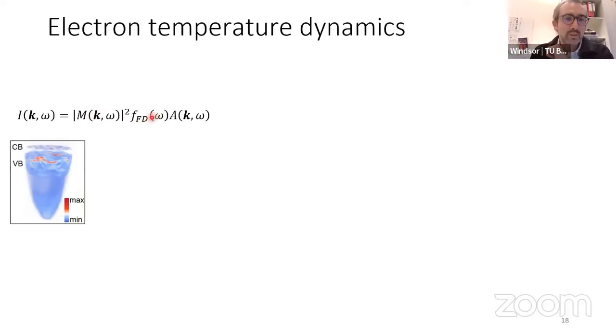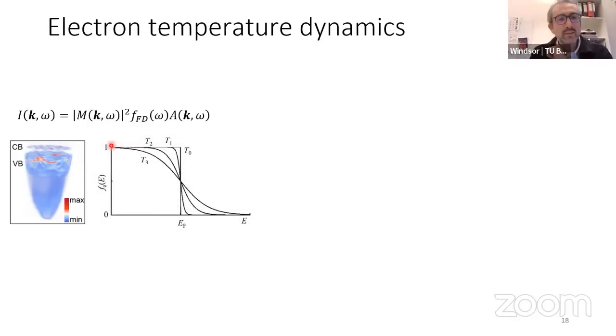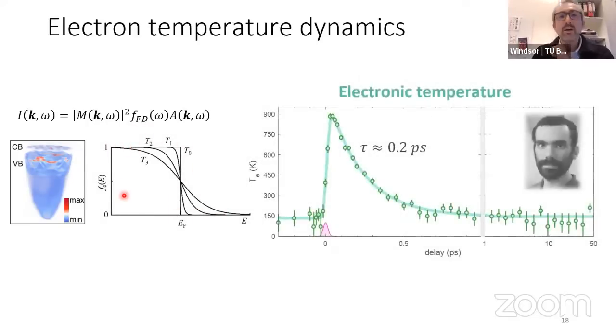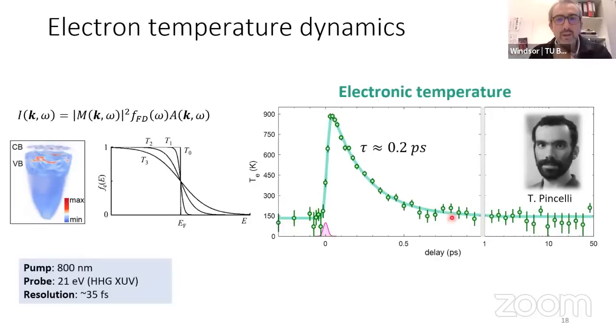We're specifically interested in the Fermi-Dirac distribution because it changes as we change temperature, and then we can extract the electron temperature. This is shown here. These experiments were done by Tommaso Pincelli, who is a colleague of ours here at the Fritz Haber Institute. What you can see here is the characteristic excitation and relaxation of the electron temperature in FGT, and we see that it's about 200 femtoseconds. That's very nice. I'm not going to go into more detail. I'm going to continue in my stamp collection now.